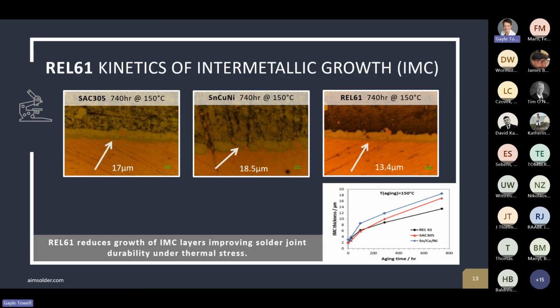So the first thing we'll look at is intermetallic growth. So it reduces the growth of the IMC layers, which can improve solder joint durability under thermal stress. And so this is just a comparison with SAC305, tin copper nickel alloy versus REL61, and we see that slightly thinner intermetallic layer after aging at 150 Celsius for 740 hours.